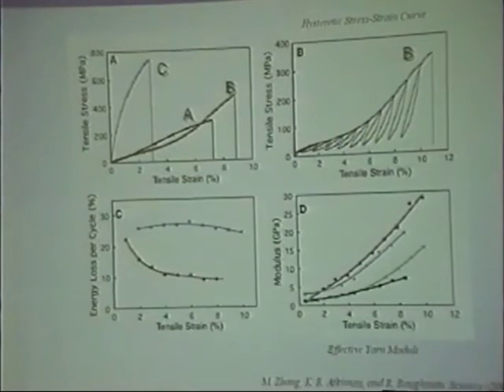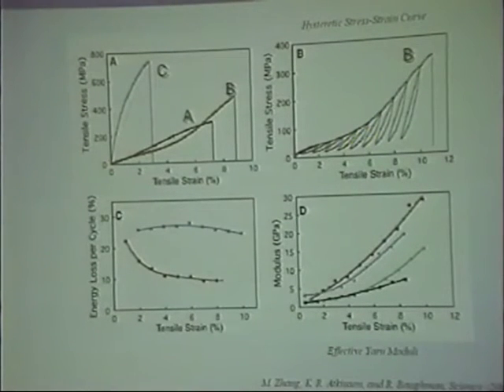And these numbers are fairly small, because if you look at B, that's about 400 megapascal. It's a very small number compared to what we are talking about, gigapascal, right? So what is happening, and that's where the problem comes in, and that's what we have to figure out. And second, we have to figure out how to improve upon that. Again, I just picked up one paper; I'm not saying this is state of the art. There are others showing 2 gigapascals, 3 gigapascals, but still not too much. And this unpublished work you were quoting, 10 gigapascal, I have not seen that, but up to 2 gigapascal I've seen in the literature.